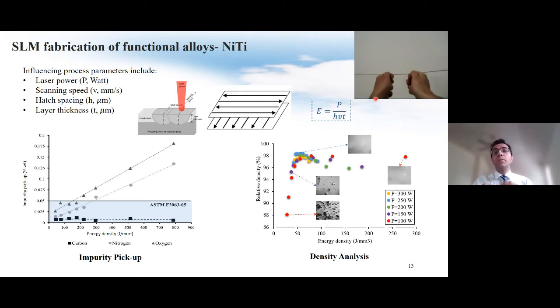There is a well-known term that relates these process parameters, which is called energy input. Energy input is equal to the power, as you can see here, divided by the scan speed, hatch spacing, and layer thickness. The very first step in optimizing process parameters is looking at impurity pickup, density, and also the surface quality of the fabricated part.